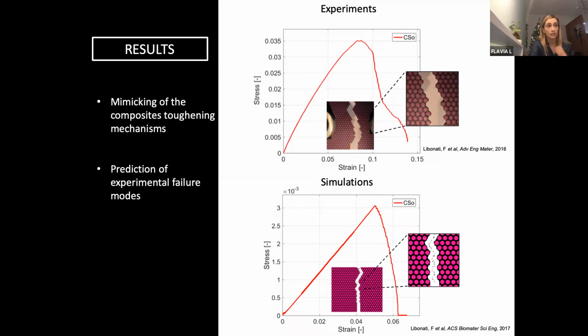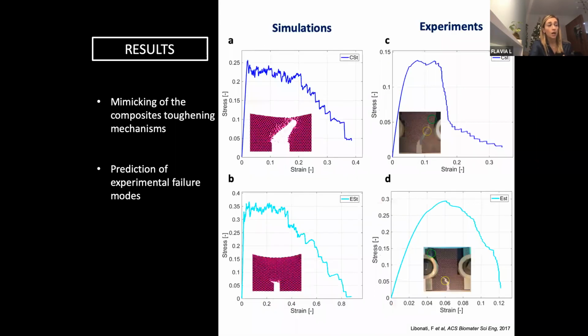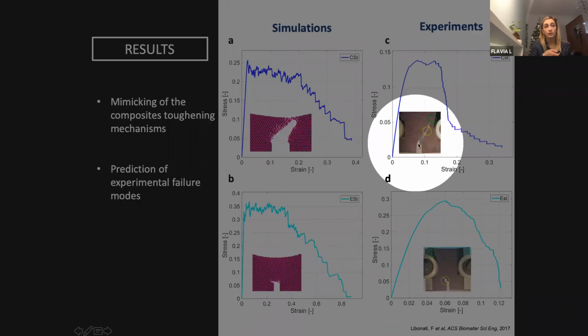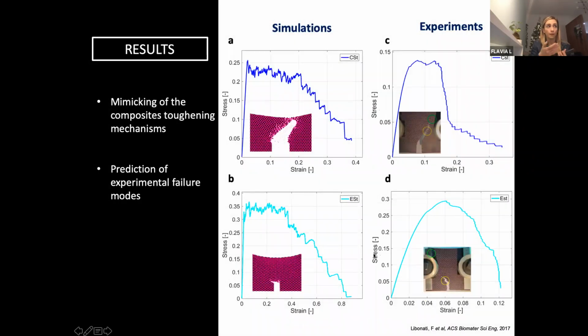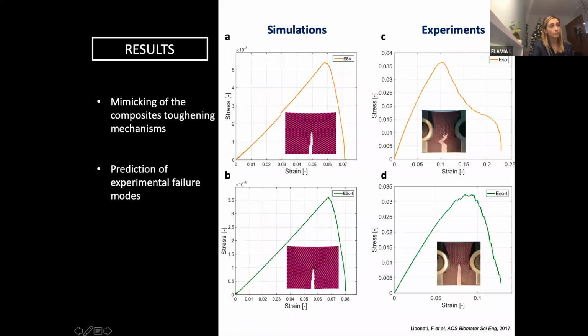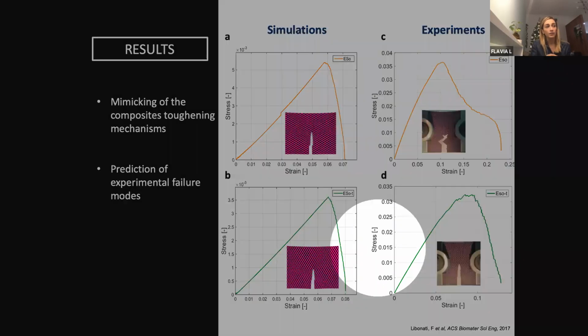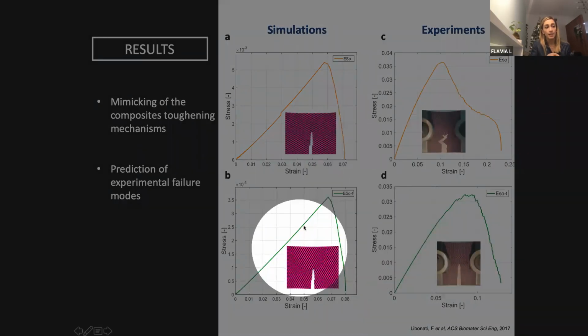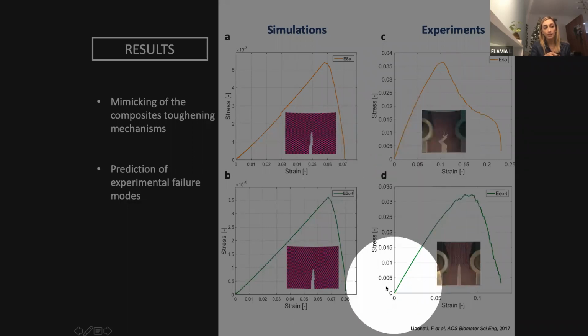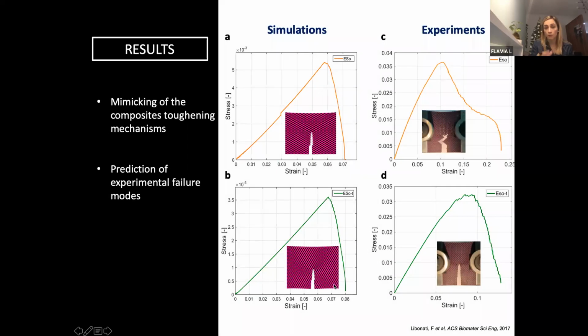So this was a circular osteon with soft matrix, but you can see the same if you look at the case of the stiff matrix and you see all these mechanisms, or the case of the elliptical osteon, or again the effect of the anisotropy. So you can see here the same material tested in two different directions and how the crack propagates in different ways.